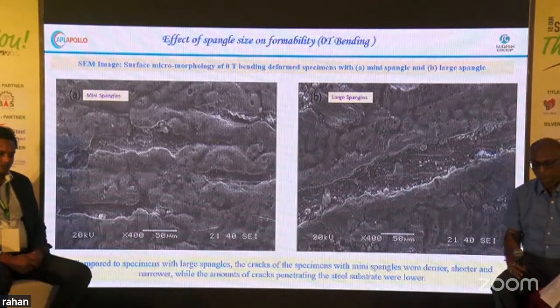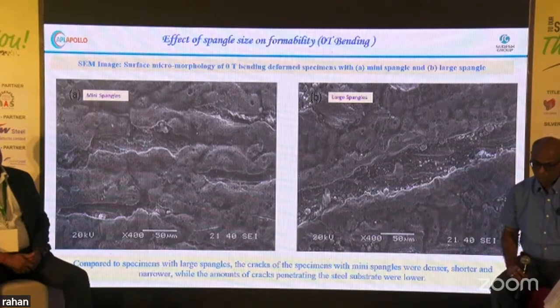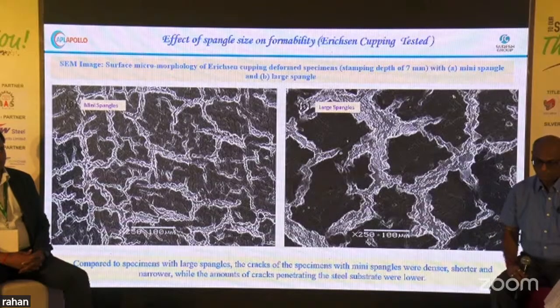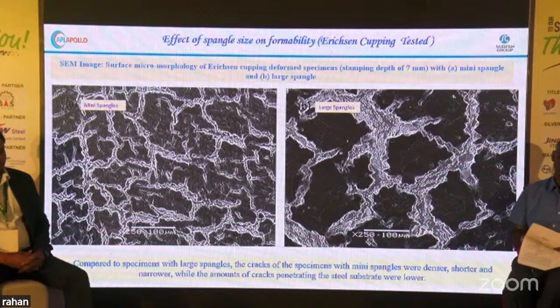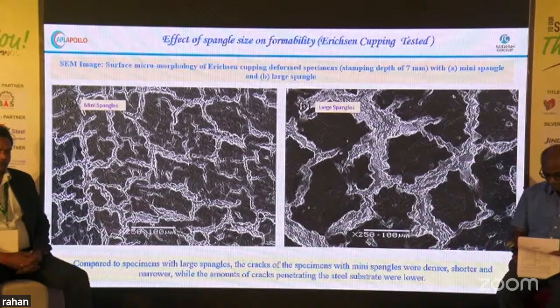Now on the left side, mini spangle is there, so it is denser and the path is short. When the corrosion product tries to penetrate the steel surface, due to the denser, shorter and narrower path, it will take longer to reach the substrate steel. On the right side, with large spangle, you can see that the path is wider and longer. The same thing is happening in the cupping test also. Here we can see that there are so many hindrances, because in the cupping test, three-dimensional deformation is happening: lengthwise, widthwise, and thickness-wise also. So here also, when we decrease the spangle size, there are zigzag paths, so it will not move easily to the substrate.